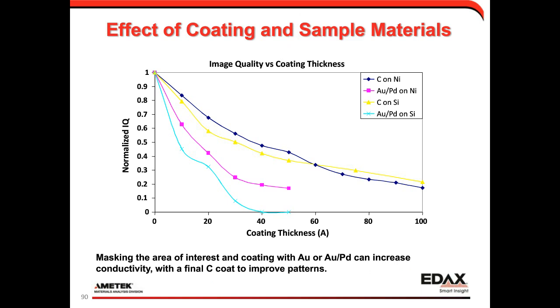And this slide just goes back to that comment of preferring carbon over gold palladium. It shows the normalized image quality as a function of thickness on a nickel substrate and also on a silicon substrate. And we can see in both cases, the carbon deposition produces a higher image quality than a gold palladium deposition would.